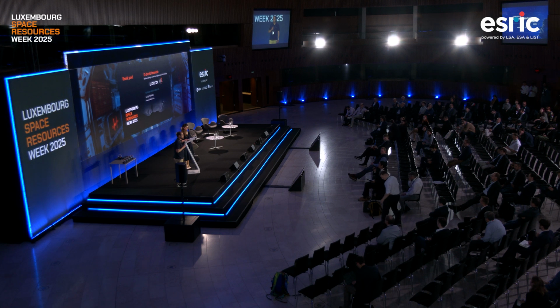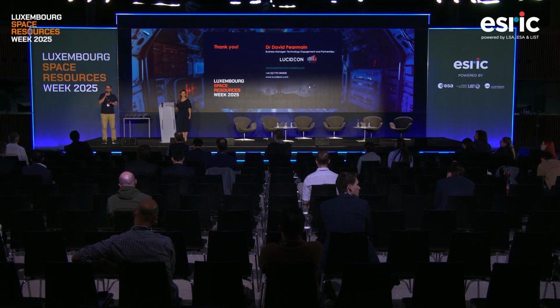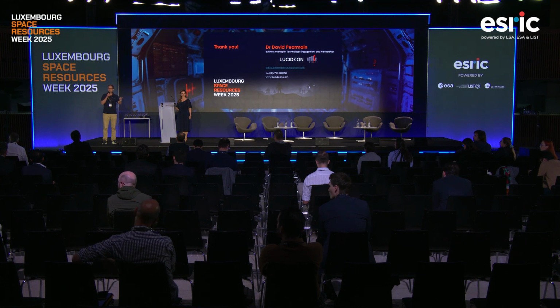I have a question regarding pelleting. Based on your study, what is the optimized pressure when making the pellet? I don't know the exact one because this wasn't a pelleting study. We did do literature reviews and found some investigations that showed 30 megapascals, and that just was not sufficient. I've seen that some of the guys from ESRIC have also done some pelleting trials on a different simulant, and both are coming out that we're pressing at around 250, 275 megapascals, and the pellets are very handleable and quite useful at that level of pressure. I can easily ask the technical team that did that work. If you want a bit more in depth, I can give you my email and we can find out.